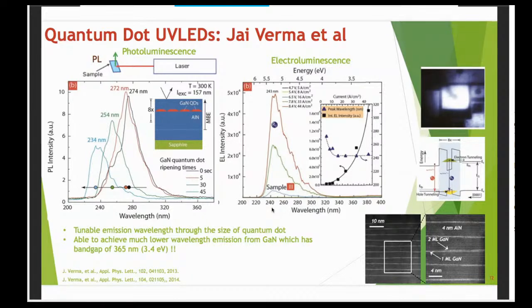So what we tried to do over here was grow gallium nitride quantum dots. That would be the well, or the dot, and in between, aluminum nitride crystals. Aluminum nitride is a large band gap material. In the band gap diagram that you see over here, this is aluminum nitride, and this is gallium nitride in between.